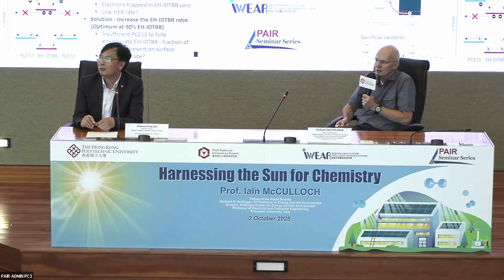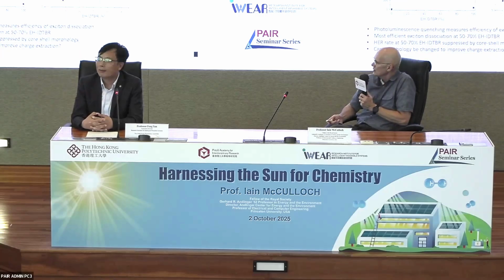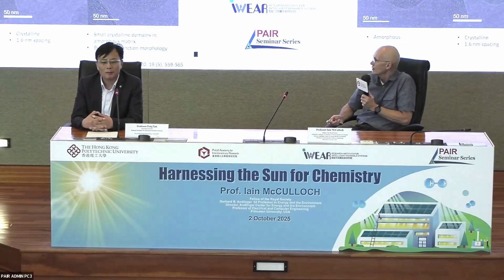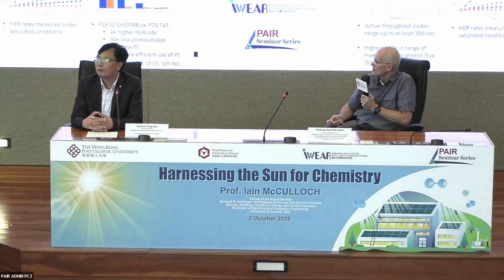Hi. I have a general question, because you shifted from nanoparticle, core-shell nanoparticle to intermixed nanoparticle, and then all the way to this type of intermixed COF or covalent network structure. Considering you are working on photocatalytic hydrogen production, the stability problem is really a big problem in this sort of covalent structure or framework. Do you have any suggestion how to address this type of stability problem in these frameworks when you're working on photocatalysis? Because it's really a big problem in the field.